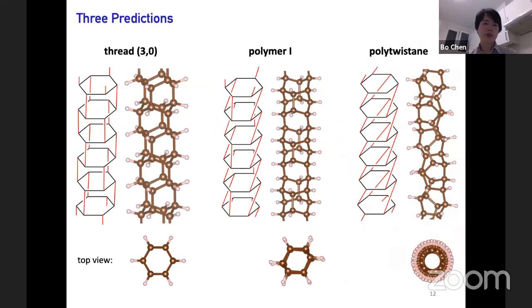So on this slide, I'm putting all these three structures together just to compare their differences. It might not be obvious that all three structures can be viewed as a stack of benzene or six-membered rings with different connection patterns between the rings. The red lines indicate the connections. You can see they are different. And polytwistane has this very interesting projection along the thread axis. It has this cylindrical shape because it is chiral and also because it has an irrational pitch. So the CH bonds are spinning around all the angles around the thread.